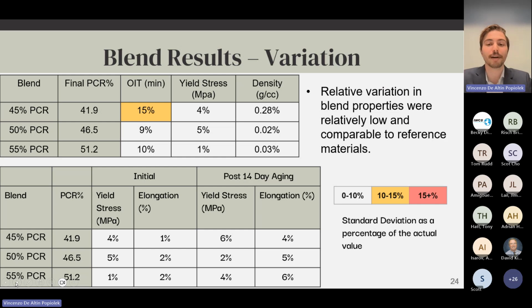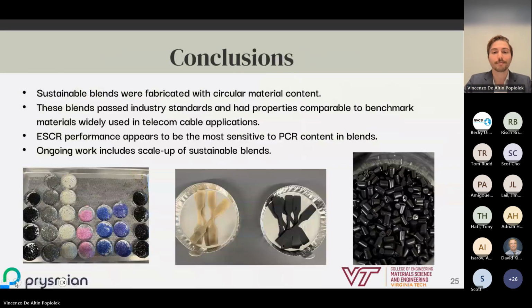Finally, we recharacterized the variability of our final blends to compare them to both the virgin and the PCR blends from the initial. And as we can see, our variation was able to be significantly decreased through this blend making, decreasing from those values between 30 and 65%, which we saw in the high PCR content blends, down to between 1 and 10% for most of our tests, with one outlier at 15%. Making these blends significantly more useful.